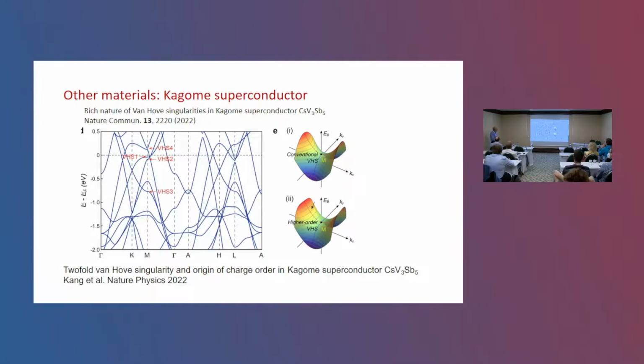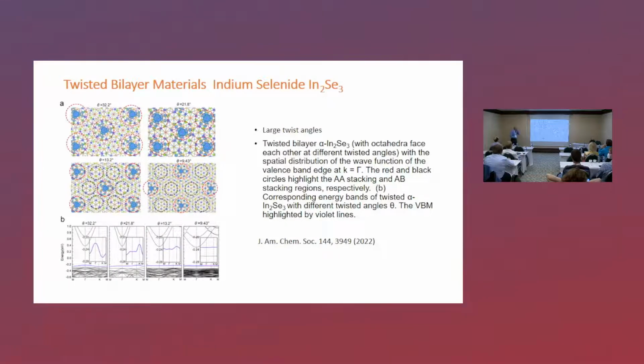The other one that, for example, is closer, a van der Waals material, indium selenide. The reason I put this there is that you can tune it to a higher order Van Hove singularity, or almost flat, what they call a flat band, but for us it is a higher order Van Hove singularity, because you see how flat it looks here. If you analyze how flat is flat, you see that there is the possibility of a higher order Van Hove singularity, but at high angles compared to twisted bilayer graphene, for example, where we need small angles to create this.